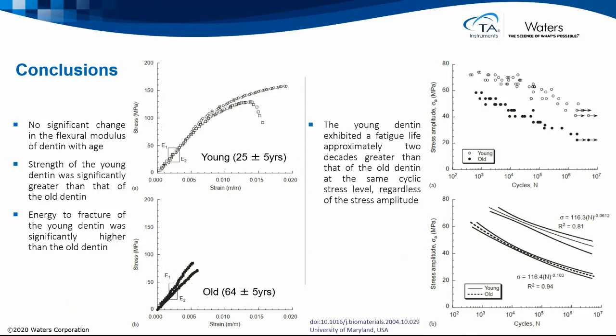So here we see a little bit more of the illustration of the data, the different types here, so that those plots we just saw would have come from the first plots on the left. This is what we call a monotonic, means one direction loading, constant rate loading, where we're applying bending to this 4-point sample until it fails. And when we do that, we're applying strain, but we're measuring a stress, and that stress goes up and up and up. And that first linear section there, you can see denoted E1 and E2. That slope is essentially the modulus of the material.